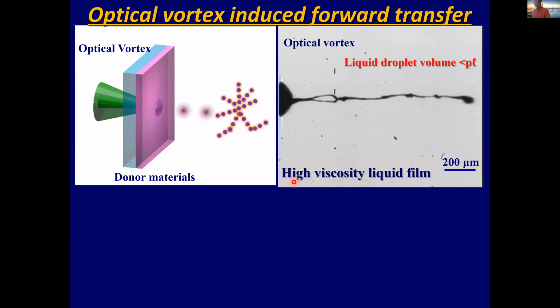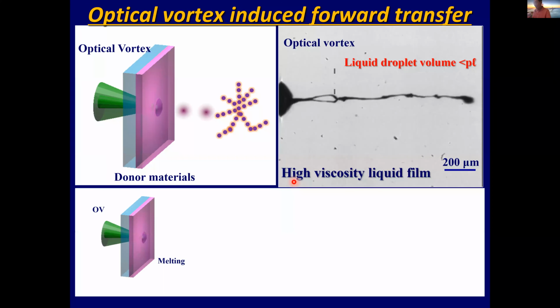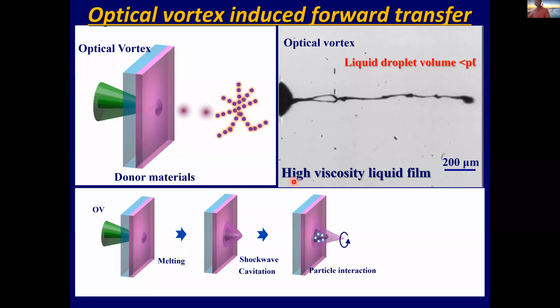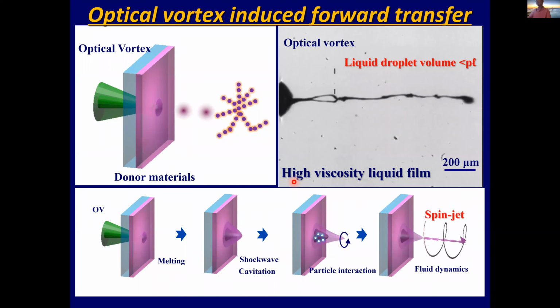Such a technique must be quite useful for spintronics, flexible electronics, and many other directions. Why has such a phenomenon happened? The optical vortex can melt the donor film. The donor film is deformed, and at that moment it receives orbital angular momentum from the optical field. Then it starts to twist, and a jet is created. At that moment, the jet is also spinning. Orbital angular momentum is transferred to stabilize the straight flight itself.